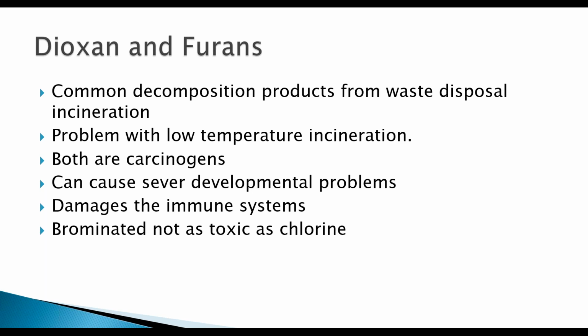Some studies over the years have shown that it is basically a problem with low temperature incinerations, around 550 degrees centigrade to 650 degrees centigrade. Both of them are carcinogens. They've also been studied and understood to cause severe developmental problems in infants, and in everyone else, it basically can damage the immune system.